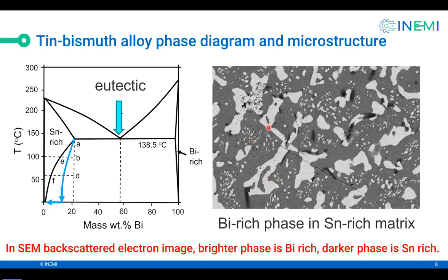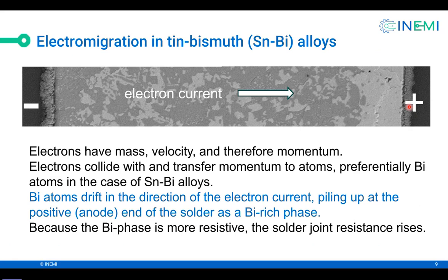So just keep in mind the bright regions are bismuth-rich, the gray regions are tin-rich. And the gray region is the matrix, and the gray region, which is tin-rich, is more conductive. So if we pump current through the sample, it'll want to go through the gray region. It will want to avoid the bismuth-rich region, which has high resistivity. So let's look at a typical planar joint under a microscope.